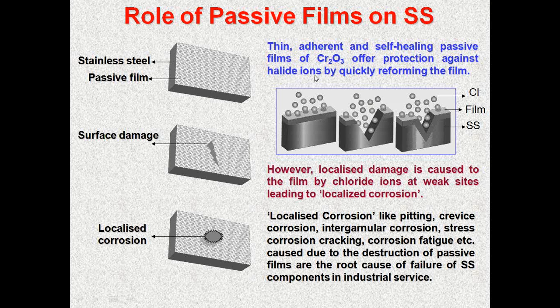Halide ions means a group of ions like chloride, bromide, fluoride, and iodide. And these ions come to the surface and attack selectively at places where the passive film is weak, forming cavities like this, which are called pits, or pitting attack. And this localized damage can lead to not only pitting, but also to crevice corrosion, intergranular corrosion, stress corrosion cracking, corrosion fatigue, etc.